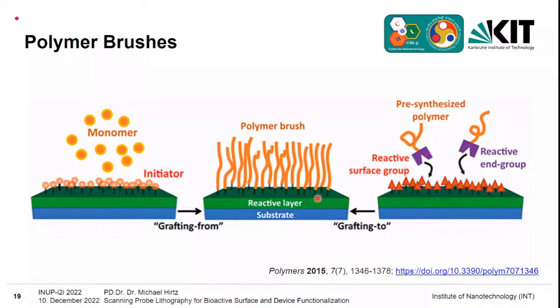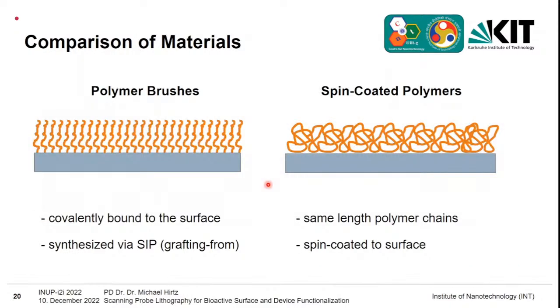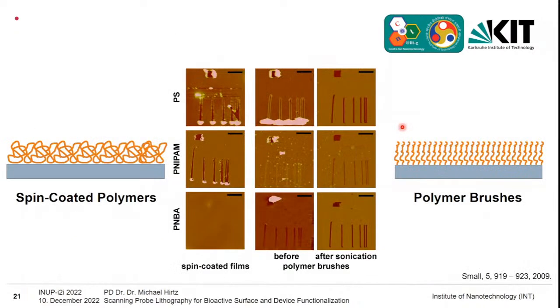But in both versions, you end up with a polymer brush, and the defining feature is that the chains are each connected covalently to the surface. So if we now compare the two materials, we have polymer brushes on the one side, all bound to the surface, and on the other side we have a spin-coated polymer, which is more like a spaghetti-like structure. Then it becomes understandable why we see this difference, and it holds also true for different kinds of